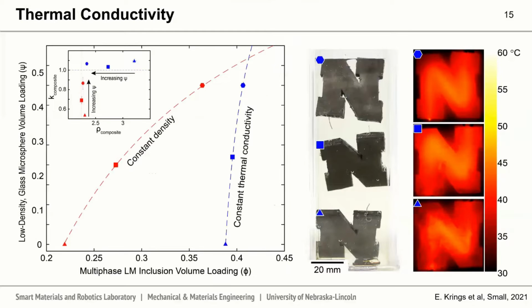From this, we experimentally verified this theoretical model. Our red line here is a line of constant density, where we're able to tune the thermal conductivity independent of the density of the composite. The blue line shows a line of constant thermal conductivity, so here we can maintain our thermal conductivity but change its density for our application. Here our goal is really to decrease its density.